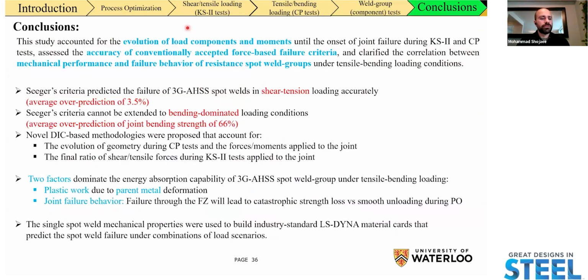So with that, I come to the conclusion part of my presentation. In my study, we accounted for the evolution of the load components and the moments that are being applied to the spot weld until the onset of joint failure during the KS2 test and the coach peel test. We also assessed how valid the conventionally accepted force-based failure criteria suggested by Seeger is under different loading conditions. Seeger's criteria can be used for shear tension loading conditions quite accurately, where we had an over prediction of around 3.5% at most.